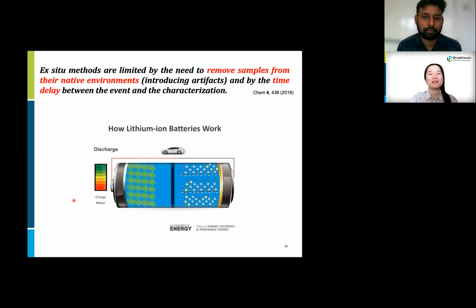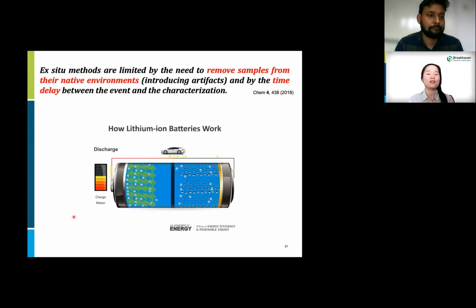I looked at cathode materials after charge in a coin cell and saw local inhomogeneity. However, this ex situ study may not reflect the real conditions in a battery system because the material is already removed from its native environment, for example, the coin cell. I also washed the materials to remove any residuals. And also there is a time delay between the event and the characterization. So to understand how the materials behave with lithium ions, we need other approaches.